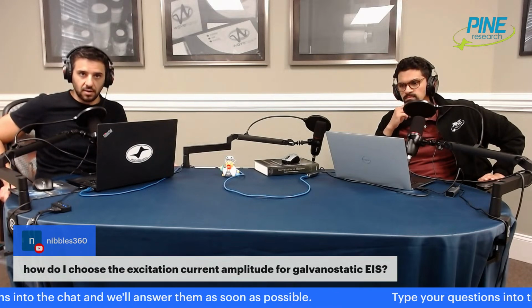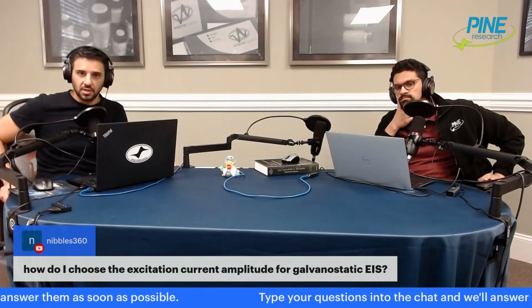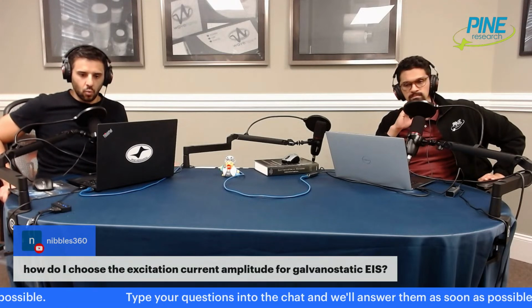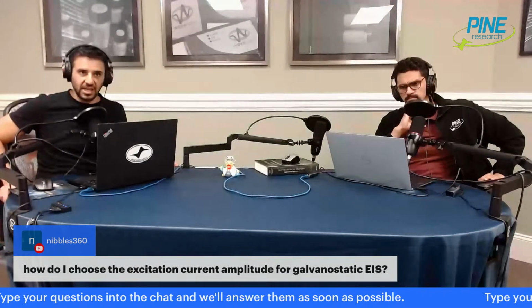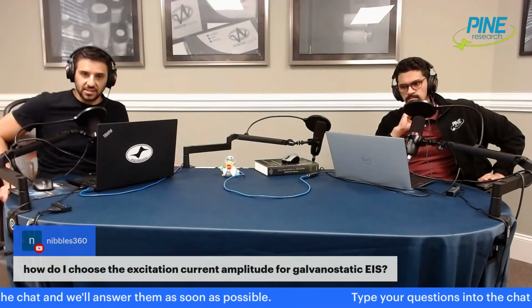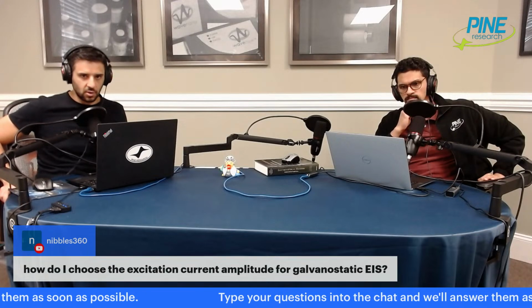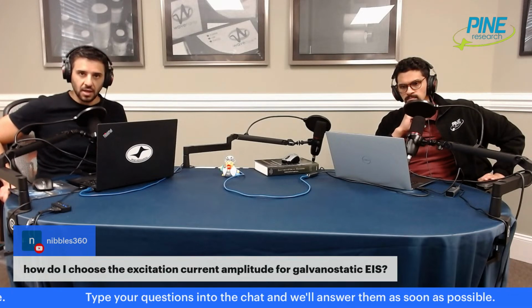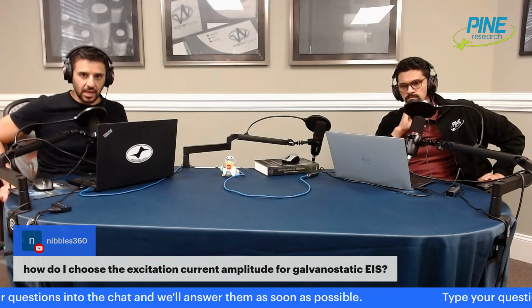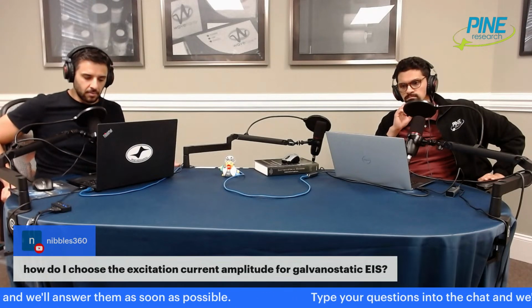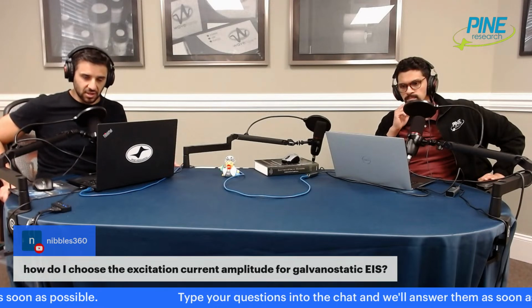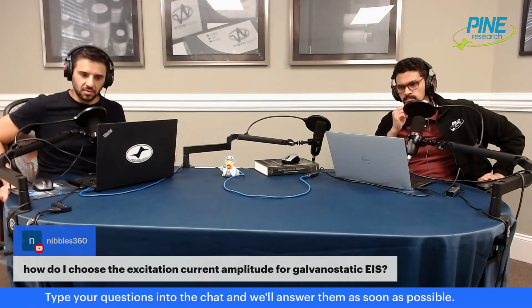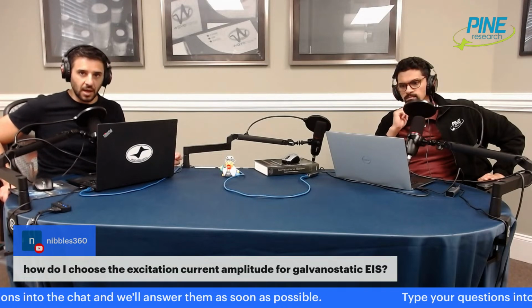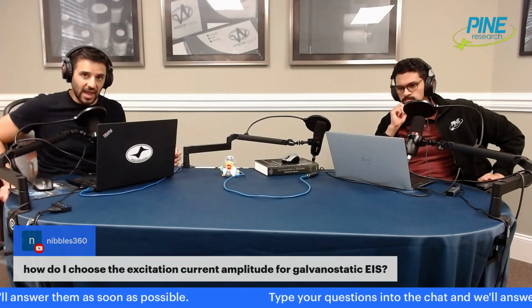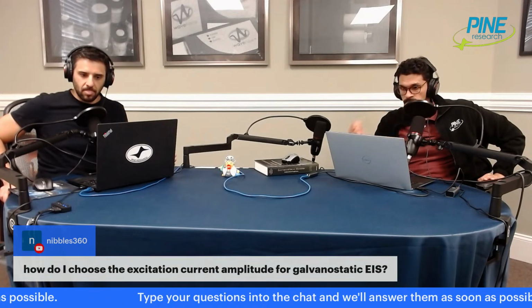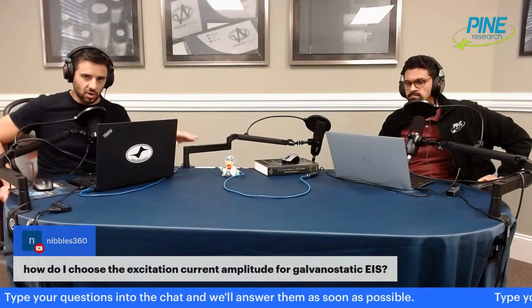For example, with batteries, you could start at something like C over 100. So for instance, if you have a 100 milliamp hour battery, that's the capacity of your battery, whether it's a coin cell or a cylindrical cell, anything, right? You could start with 1 milliamp amplitude. That's C over 100, so 1/100th of the capacity, that amplitude could be a starting point. Most probably that won't be enough to get you good data, but that's okay. So in general, that's a metric that you can try for a battery.